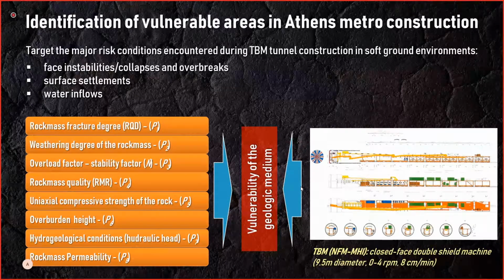And each one of them actually corresponds to a behavior type that can affect tunneling. For example, the most important parameter designing the TBM is the UCS. And of course, the RMR classification used to describe the stand-up time of the excavation, or the overload factor, can assess face stability. On the other hand, the selected method of tunneling has its own qualities, characteristics and needs. In this matter, the thinking is that once we establish an assessment of the compatibility between the construction method and the actual geotechnical setting, we can then easily know if we have a good situation or a bad situation for the tunneling process.